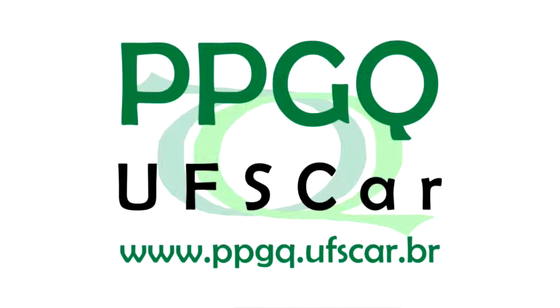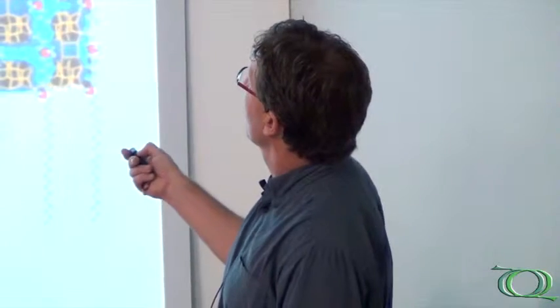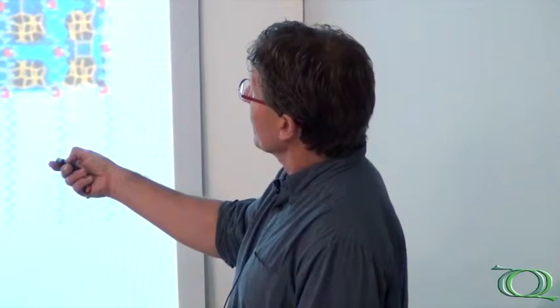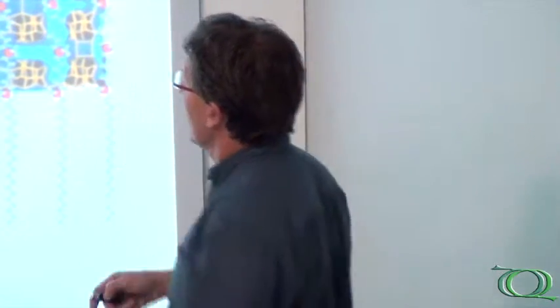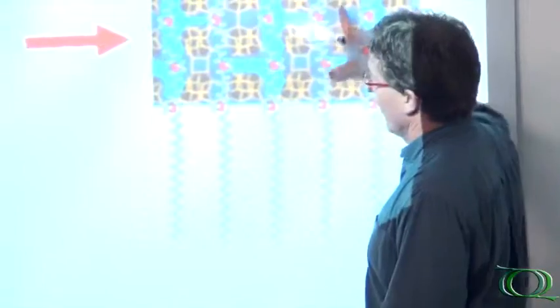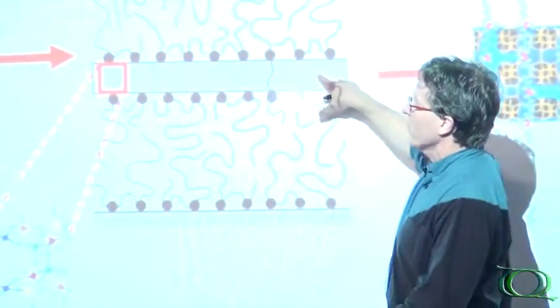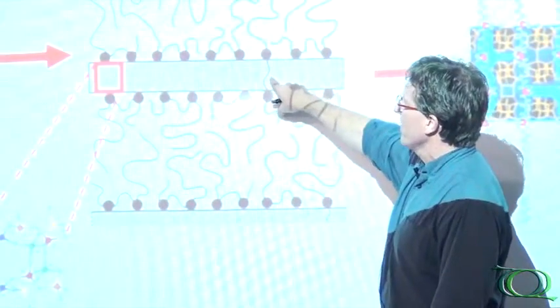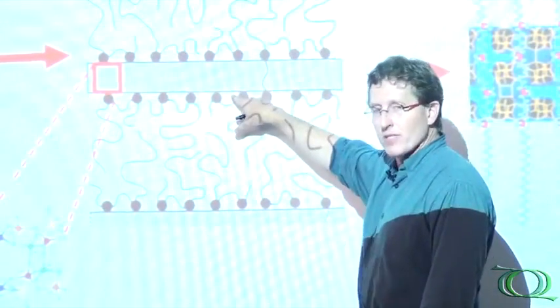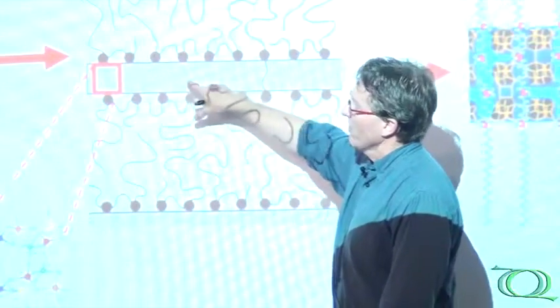So the question is how do these mesostructured zeolites develop? The hypothesis is that the amorphous mesostructured materials, these mesostructured frameworks, transform into 3D porous crystalline structures and they do into like the zeolite type frame but they do so through a layered silicate intermediate. The layered silicate intermediate corresponds to the same layered silicate intermediate that I showed in the example.